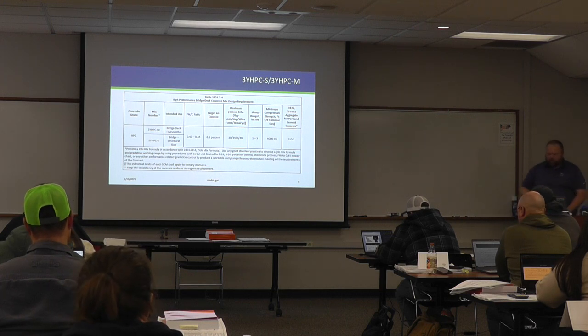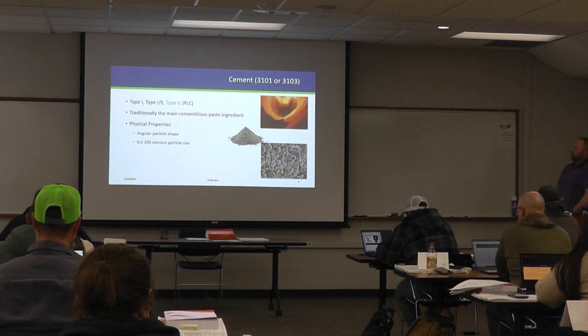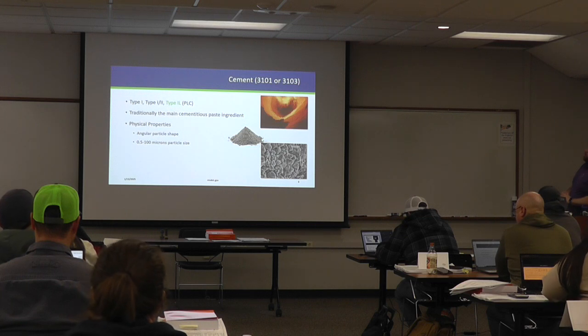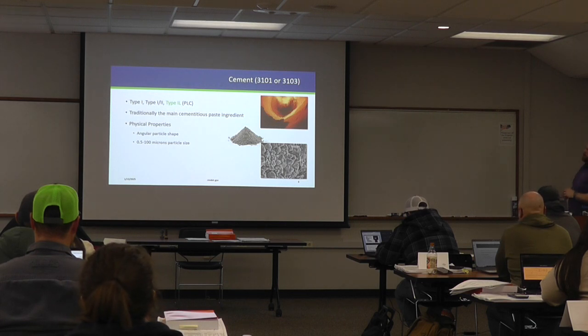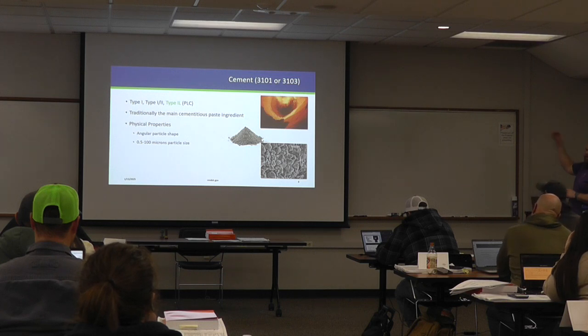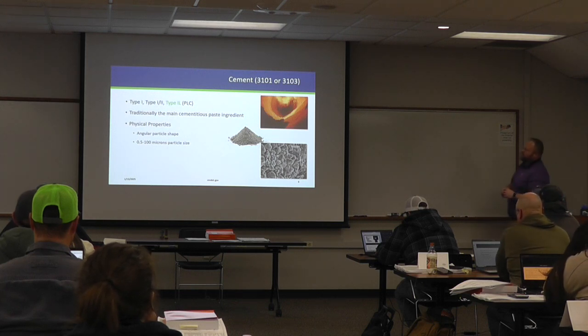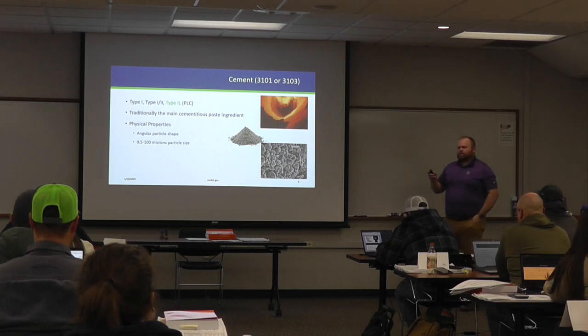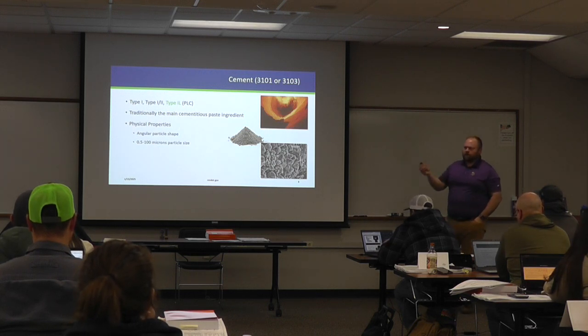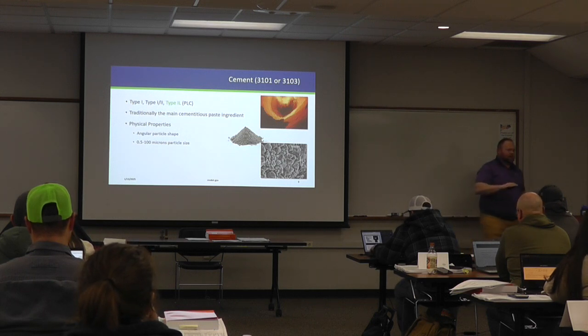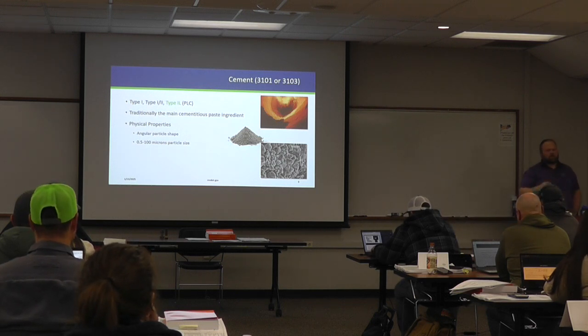So what goes in, when we're talking about concrete, obviously we use cement. Cement makes up our paste. And, you know, historically we were using type I and type I/II cements, but about 3-4 years ago in this state, all of the suppliers, save for one up in the Duluth area that brings in cement from Turkey, are only giving ready-mix producers type 1L cement. And all type 1L is, is type 1 with about 10% fine limestone ground mixed into it. And we don't really see any property changes in the concrete using type 1L cement.